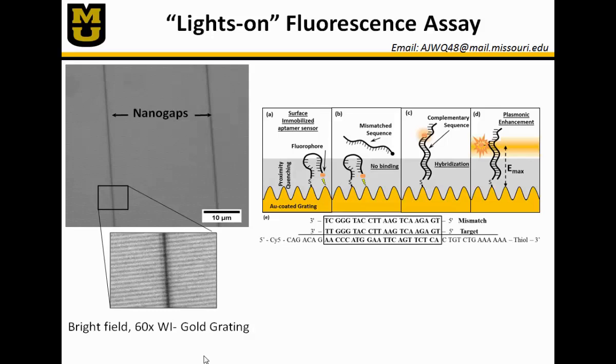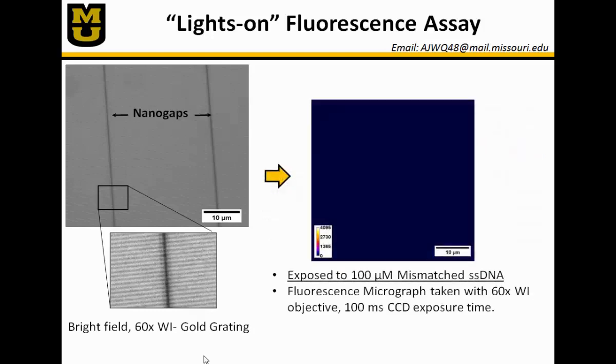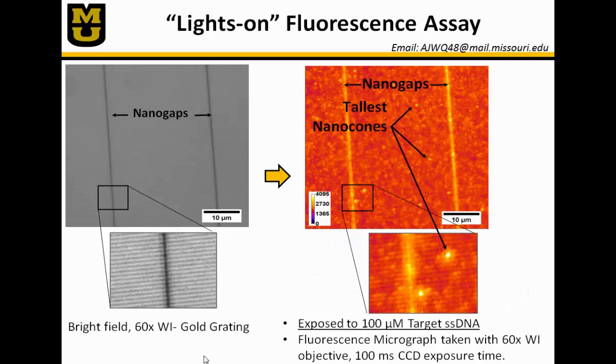So to give you some of the results from that assay, on the left we have a bright field image using a 60x water immersion lens on a gold grating. And we have enough resolution that we can begin to see the grating ridges as well as 2 nanogaps that are cutting through that gold grating. Now if we expose this grating to a mismatch sequence, the fluorescence is very low, as we would expect. But if you expose it to a complementary sequence, you can begin to see how high the fluorescence intensity is located all over this grating. So you can actually see the grating ridges and their enhancement, as well as the enhancement by these large nanoconical structures and the nanogaps that are located inside of this grating.